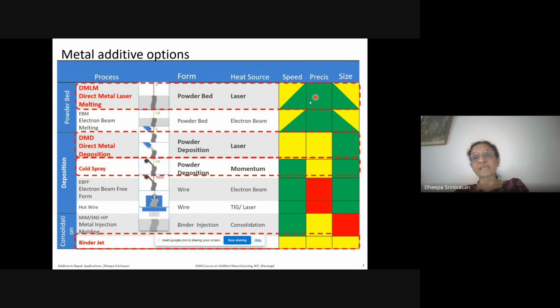If you want to go to great speeds, perhaps this cannot churn out. It's a little bit of a slow process. All are slow, but relatively speaking, the direct energy deposition is much faster as compared to the laser powder bed fusion. If you want to make large footprints, 800 millimeter by 800 millimeter by 1 meter parts, then you're not choosing the right technology if you go to direct metal laser melting. Instead, direct energy deposition is the best, and so on and so forth.